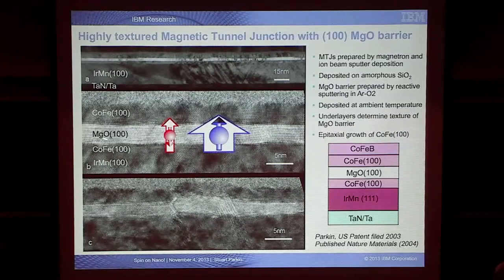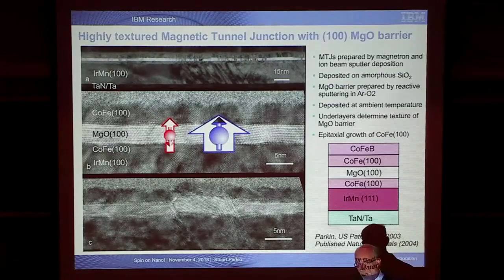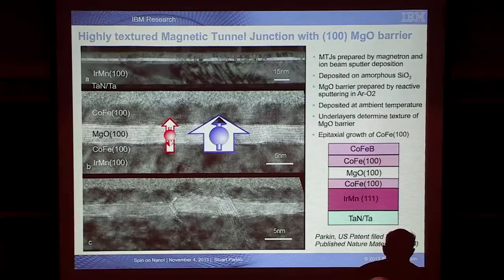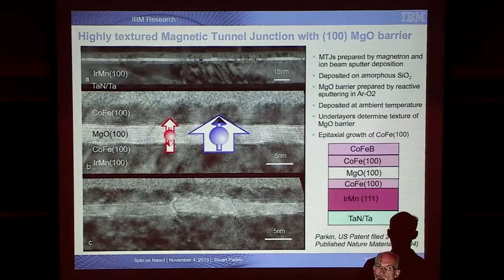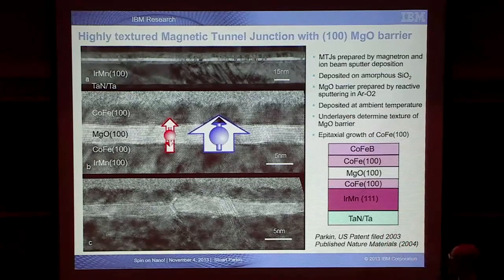And so essentially, it's an amazing result. This crystalline, non-magnetic material essentially filters out, or spin filters, the electrical current, so that instead of having a current that might have been 50% spin polarized, it can be nearly 100% spin polarized. So this was a remarkable theoretical prediction which we first showed experimentally. And what does it mean?